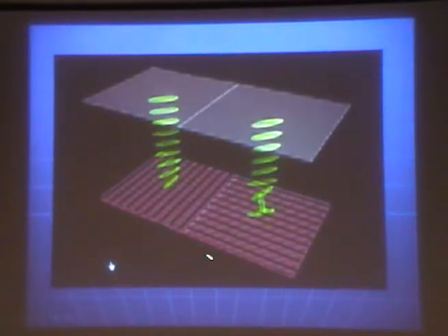And on this domain, this generates a 135-degree twist. And it can be proven that if you have a twist larger than 90 degrees, there is an instability of alignment. By increasing the electric field, at some point, the stability on the surface is overcome by the electric field induced torque.